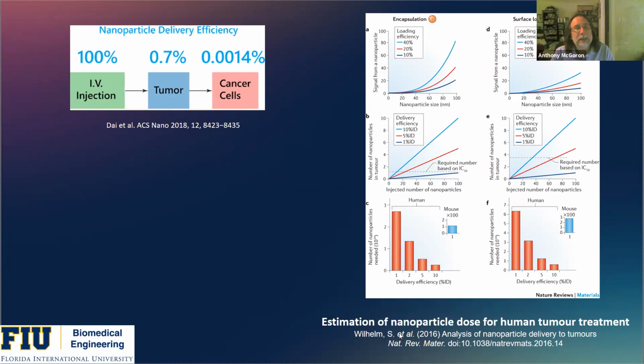The same group, Wilhelm, a couple years earlier, had predicted, based on a study that they did, comparing if a drug is encapsulated into a nanoparticle, for instance, in a polymer or a liposome or a mesoporous particle, or if it's just attached to the surface of the particle, how much signal would be received, because this particular study was focused primarily on imaging agents delivered by nanoparticles, not therapeutic agents. But nevertheless, of course, we get much greater signal or much greater therapeutic effect, we would assume, if we have a higher loading efficiency.